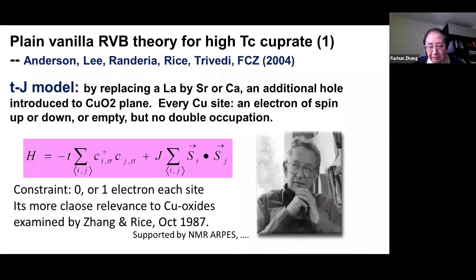The most important advance in that direction was made by Phil Anderson, who proposed a t-J model for the system. He made that conjecture, the RVB theory, in 1987, just a few months after the discovery of high Tc. And we wrote a review-type article we call the plain vanilla RVB theory for high Tc. It contains a few important things. The first thing is the model, which we call the t-J model on a 2D square lattice. That's because when you dope lanthanum by strontium or calcium, you introduce additional holes. Those holes will be on the copper-O2 plane.